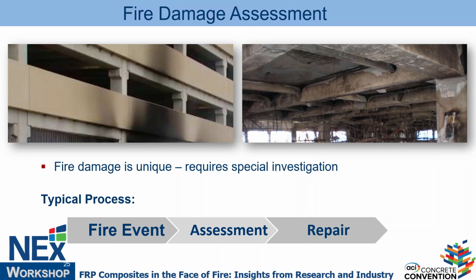You can take samples of the steel and test them to verify residual capacity if you're planning to keep the steel. And you can do cores. You take cores and do petrographic analysis on it to figure out the depth of the damage if you want. Although in my experience, just simply doing the sounding and the drilling can give you a very good indication of the depth of the concrete damage that you need to address.